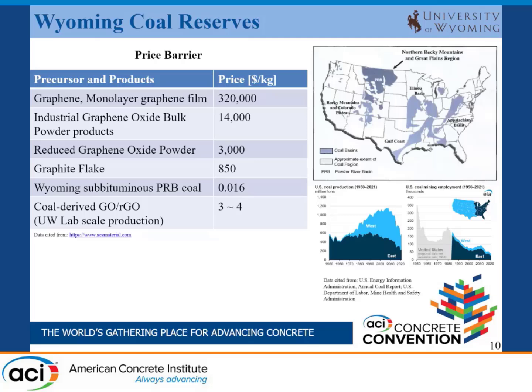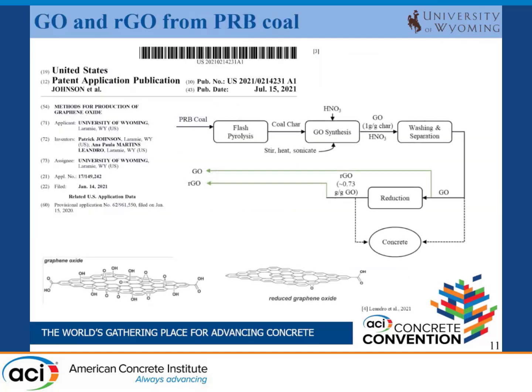And as I previously said, the graphene oxide production is at the lab production level. So still we are calculating that the price of the graphene oxide is $3 to $4 per kg, whereas in the whole world or in the USA market, we see that graphene itself has a price of $320,000 per kg, and graphene oxide is $14,000 per kg. So in the first phase, we try to reduce the price from $14,000 to $3 to $4 per kg of graphene oxide. And we select subbituminous coal from the 4 types of coal because of its carbon properties, like it has 35 to 45% carbon in it, and it has a lower heating value than bituminous coal.